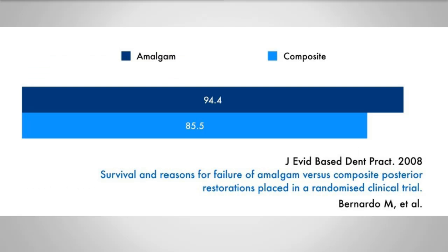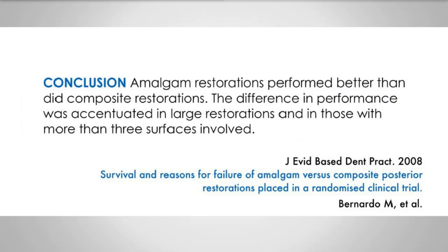When we look at amalgam versus composite and what the evidence tells us, this is from the Journal of Evidence-Based Dental Practice in 2008, and it was looking at survival and failure of amalgam versus posterior composites. Now actually amalgam came out better than composite, and the conclusion from this study was that they were doing better, and the difference was particularly accentuated in large restorations and in those with more than 3 surfaces involved.